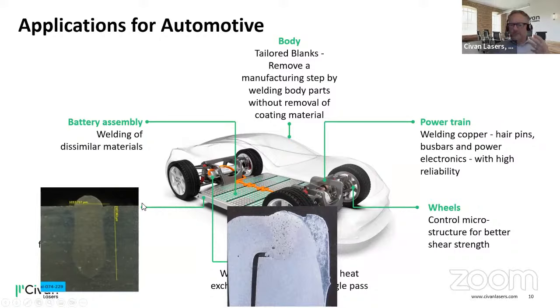But in order to do that, you have to weld very fast, and that's where you get to 30 meters per minute, for instance, and that is where humping comes in. So this is basically a technology that can move the speed barrier of high-speed aluminum welding by quite far. Right now, it's actually by a factor of 2 if we look at other solutions on the market.